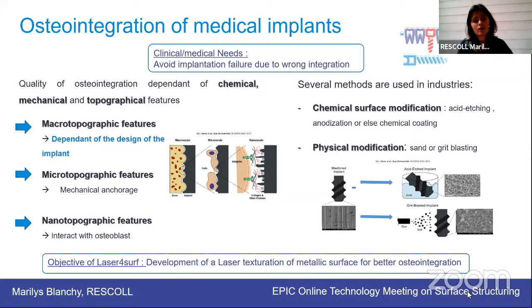Nowadays there are several methods used, as I said. They use chemical surface modifications such as acid etching, anodization, or chemical coating. Or there are physical modifications such as sand or grit blasting. The main limitations of these currently used methods are, first of all, they use harsh solvents. They are not very controlled in terms of the topography and the features, so it's random features on the surface. We cannot have control of directions such as anisotropy of the features on the surface. And finally, it changes the chemistry on the surface of the implant. And from a regulatory standpoint, it's sometimes difficult to be approved.